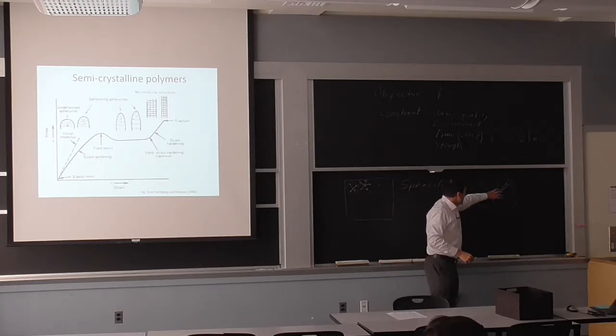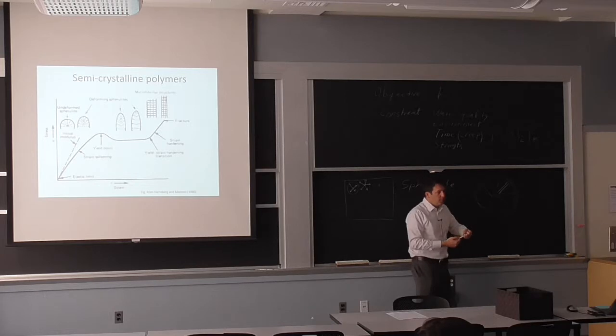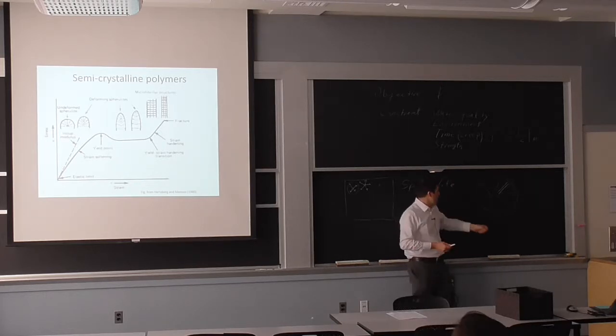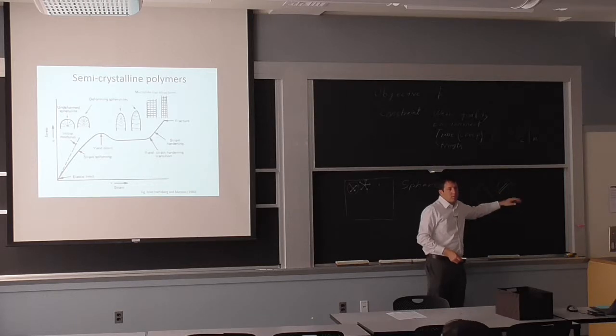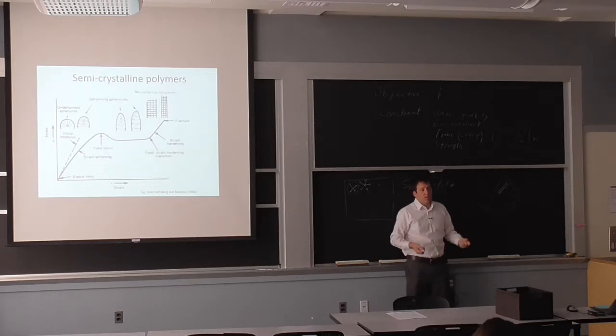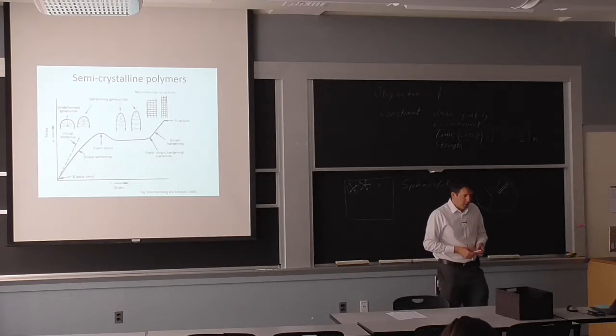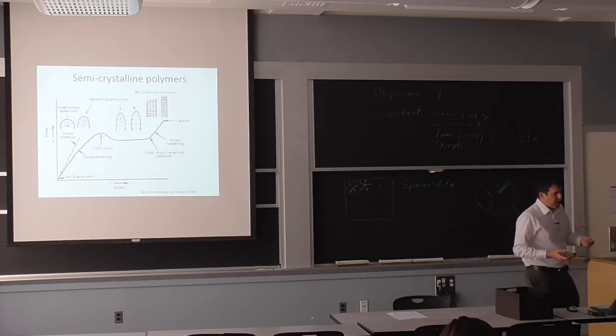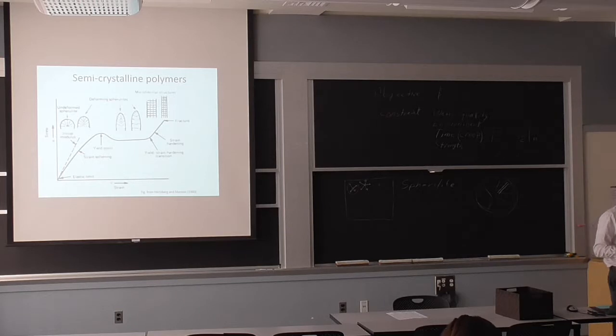So that's a little bit how you start the deformation, and as you keep pulling it, you are stretching the chains, and you are aligning the spherulite through that process as well. So you can essentially increase the strain. Doesn't really show here. You can increase the strain by perhaps a factor of 2 or 3 before you get to this very microfibrillar arrangement. That is, of course, if you don't break it.